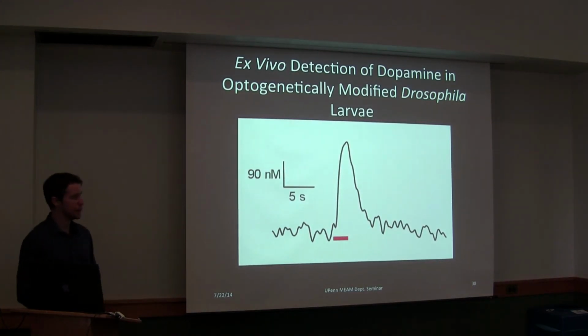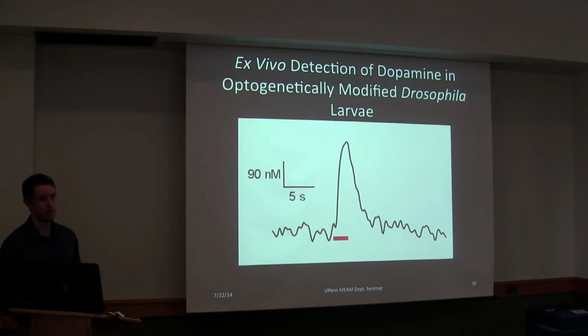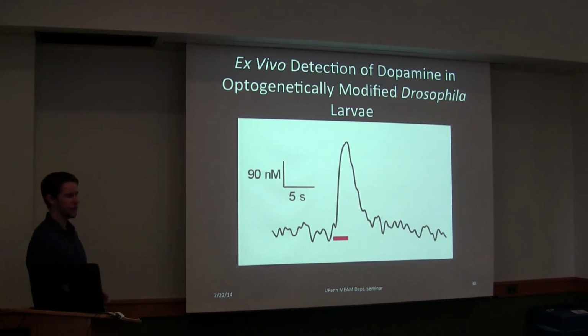We can also look at the ex vivo detection of dopamine in optogenetically modified Drosophila. Drosophila are nice because you can genetically modify them. In this case, they genetically modified these flies to respond to red light, so whenever you shine a red light on them, they release dopamine. It's a relatively new technique, and they have these larvae with ion channels that respond to this red light. So they stuck a CNP in the nerve cords of these larval flies, shined a red light, and were able to measure dopamine concentrations in real time. So basically we characterized and demonstrated direct application of the CNPs for measuring these neurotransmitters in flies.